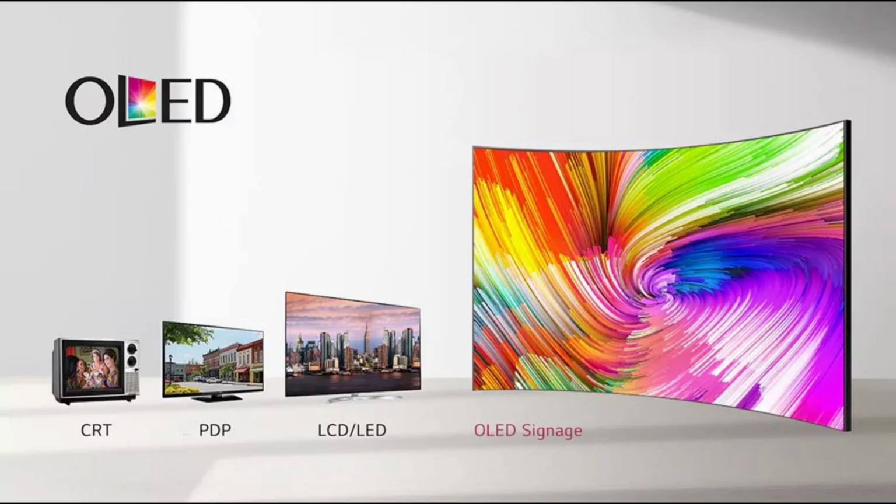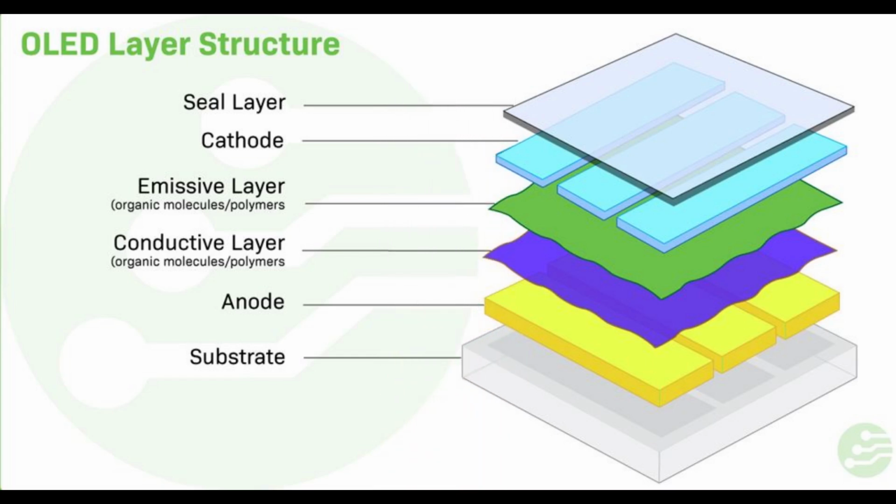However, small molecule organic dyes are prone to fluorescence quenching in the solid state, resulting in lower luminescence efficiency. The doped OLED devices are also prone to crystallization, which reduces the luminescence and efficiency of the devices. Therefore, the development of devices based on small molecule electroluminescent materials is limited by high manufacturing costs, poor stability, short life, and other shortcomings.